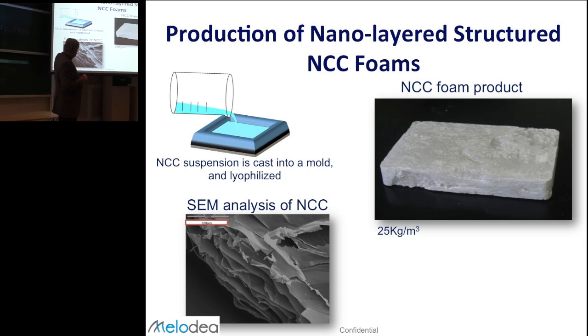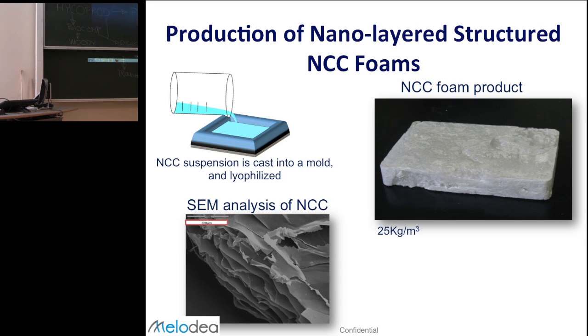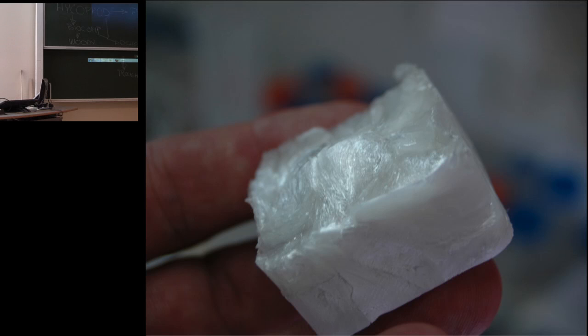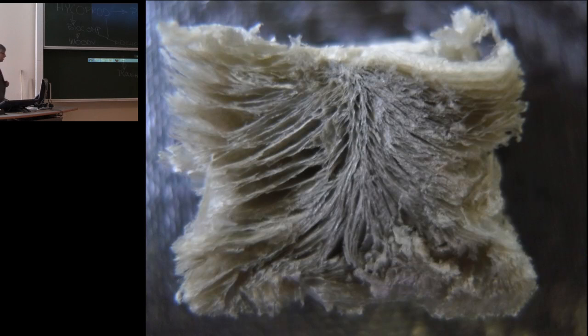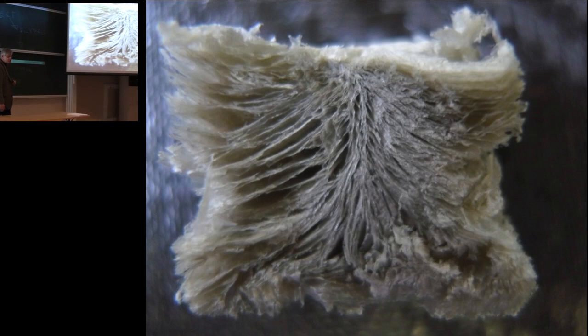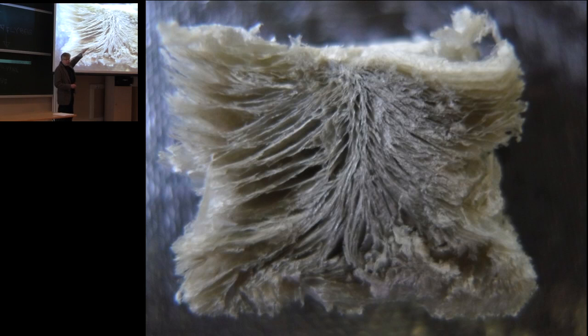First of all, we did this nanocellulose and we made it into a foam. We made a suspension with 2.5% nanocellulose fibers in water. And then we took away the water, and the weight will become 25 kilo per cubic meter. That is extremely light. And though it's pure wood, pure cellulose, it is a very good insulating foam. But when talking about raw materials, here you have the foam. And we can predict, or we can monitor, decide in what direction these nanocellulose fibers should be. So I can make a foam where I put the fibers in a certain direction, all in this direction, or what I want.